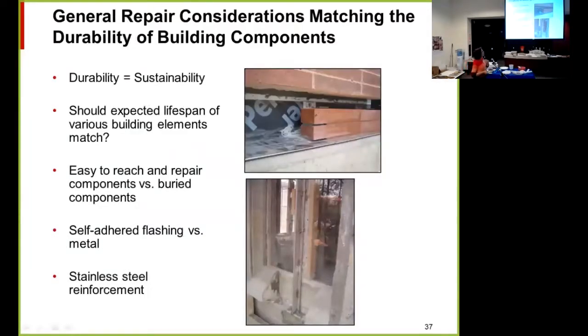In thinking about repairs, of course, we all want our repairs to be durable. If you ask me, durability and sustainability are almost the same, because if you do a repair and it's sustainable, then you're not going back and spending energy to keep working on that building. So one thing to think about is the durability of the different components in a repair. For example, putting a stainless steel edge on a flashing makes it more durable than if it was just the perma barrier. Using stainless steel for reinforcement rather than galvanized steel or mild steel makes a more durable repair, even though you can't see it, and those pieces are all hidden.